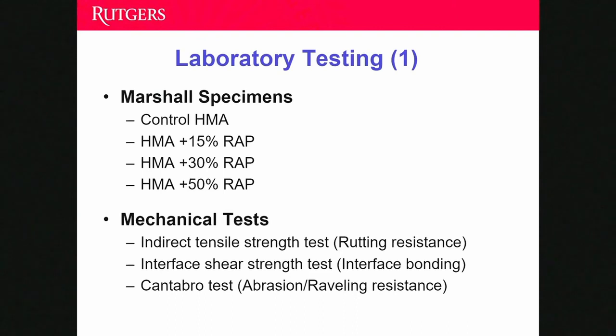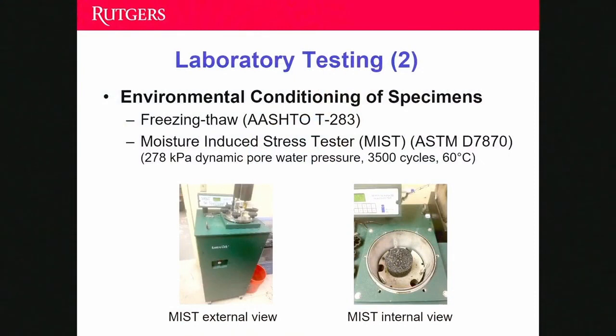We selected 3 different mechanical tests to evaluate the performance of the patching material based on the primary failure modes. We did the indirect tensile strength test to evaluate the rutting resistance of the patching material, and the interface shear strength test to evaluate the interface bonding condition. And we did the Cantabro test to evaluate the abrasion resistance. Because the RAP material may have some moisture sensitivity, and also based on our survey response, water is the main reason for pothole failure,